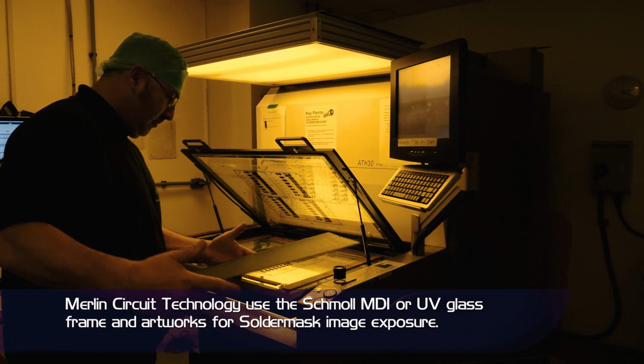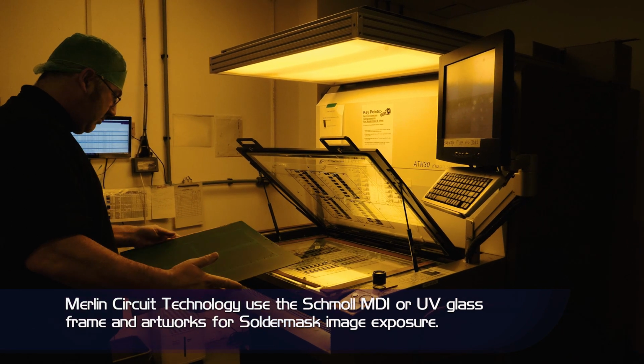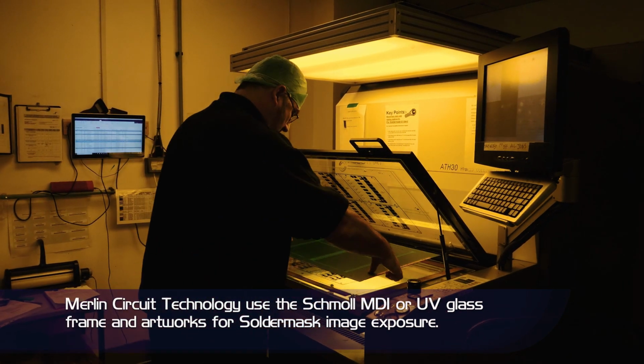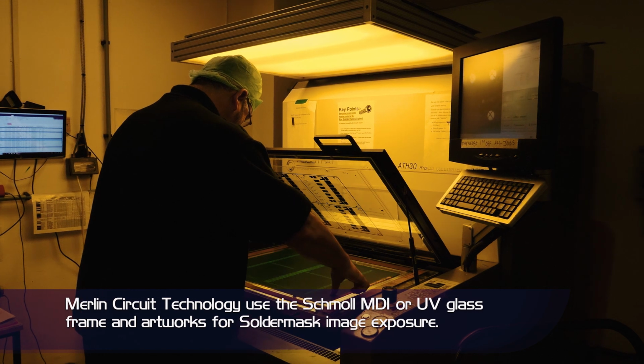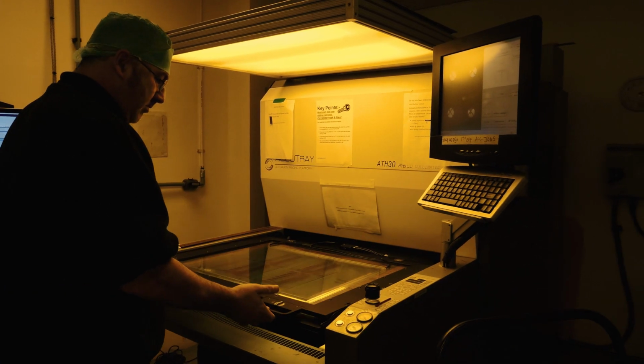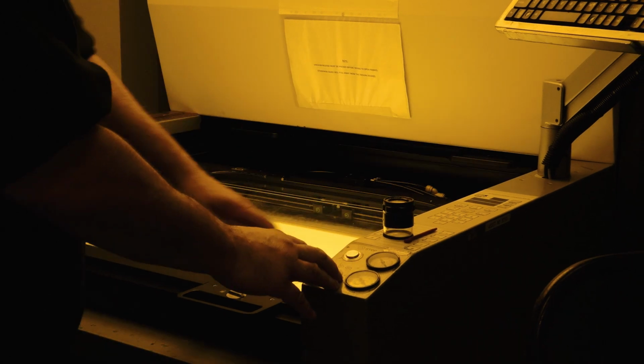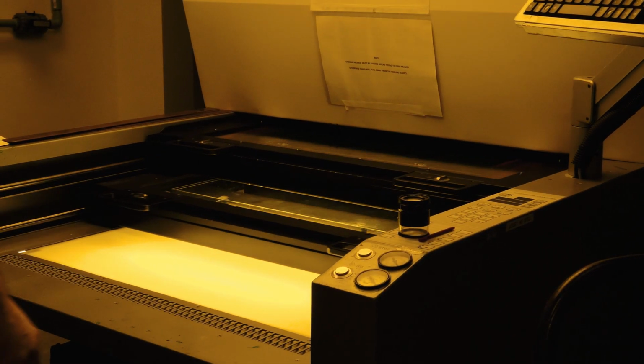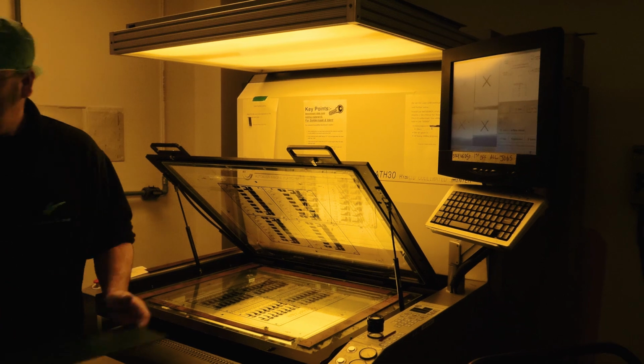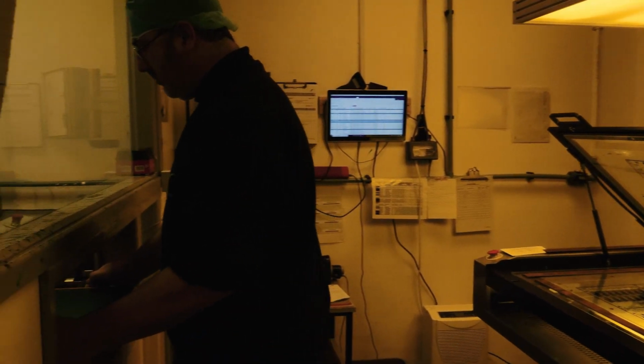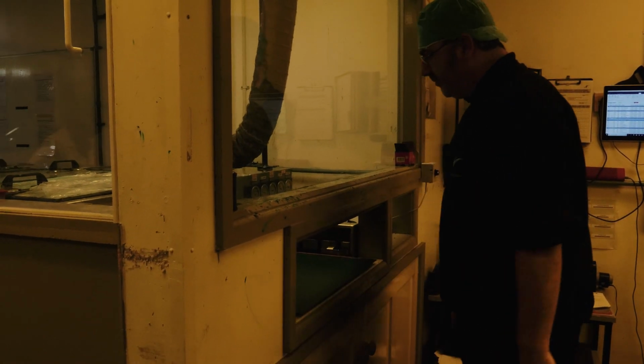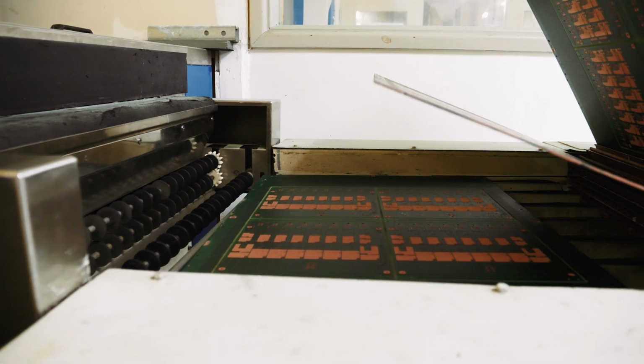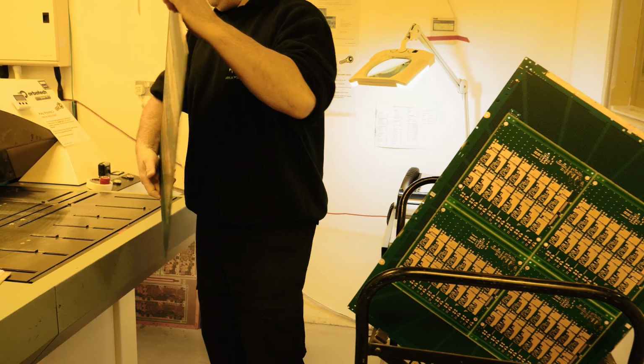The panel is then imaged through a mask, black and clear, using UV light. Areas where the mask isn't required, solderable pads etc., are masked from the UV light. The Schmoll MDI machine can also be used to expose the solder mask. This is used when very fine apertures or tight alignment is required, generally for small BGA component footprints.